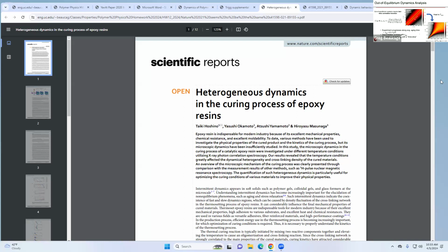So, right. So these pictures are cool. We can throw them in our paper, whatever, but they don't tell us anything about the actual physics and the timescales, right? So how do I get that relaxation time out from this figure? So what we do schematically is I basically track along that average aging time, and I make a little slice or a cut. And I say, what is that decorrelation going to look like right along this line here? Essentially saying, if I started my XPCS experiment at aging time 1, aging time 2, let me look at the correlation from that point in time, right? So we're doing these slices along that.